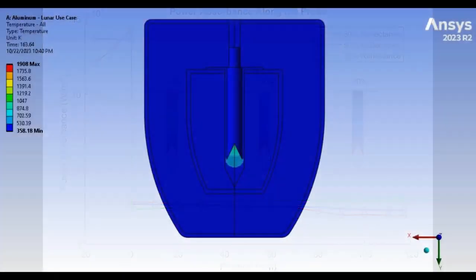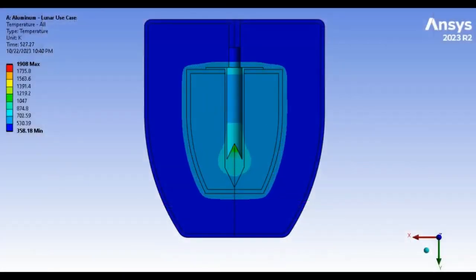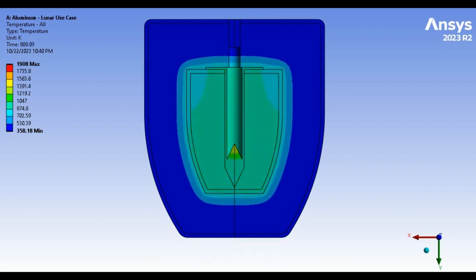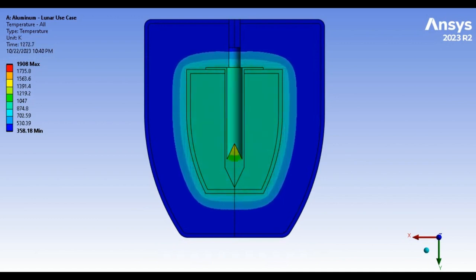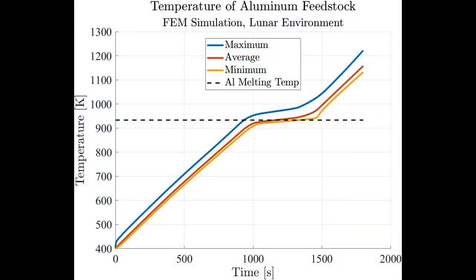With boundary conditions set by the ray tracing study and a finite element model validated by experiment, the team studied the heating of ISRU-derived feedstocks within the true lunar use case, with results showing that ACRE will be able to melt and cast 1.3 liters of aluminum feedstock in approximately 25 minutes, making it a promising candidate for the fabrication of mixed aluminum regolith metal matrix composite roads across vast areas of lunar surface.